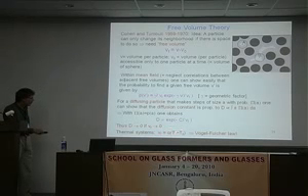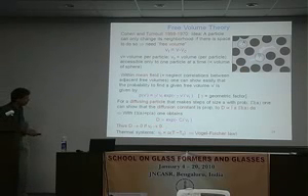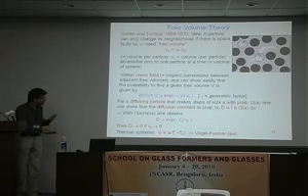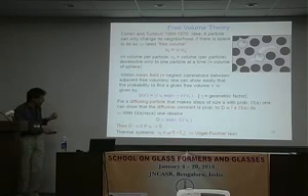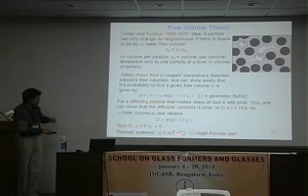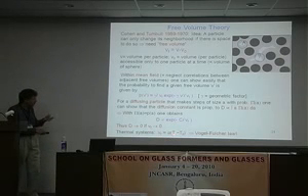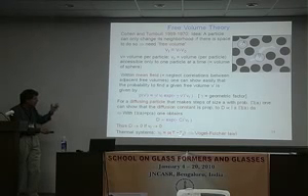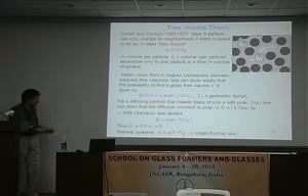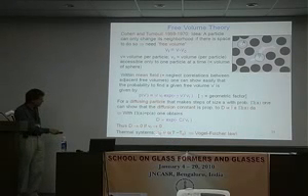And so this is all good for hard spheres, but if you want to have a thermal system, you say that this free volume is related to temperature minus a certain fudge temperature T naught, at which you want something to happen, and the alpha is just the thermal expansion coefficient. So volume is related to temperature by the thermal expansion coefficient, and you say that at the temperature T naught something happens. So if you plug in this Vf in this expression here, you get again the Vogel-Fulcher law.